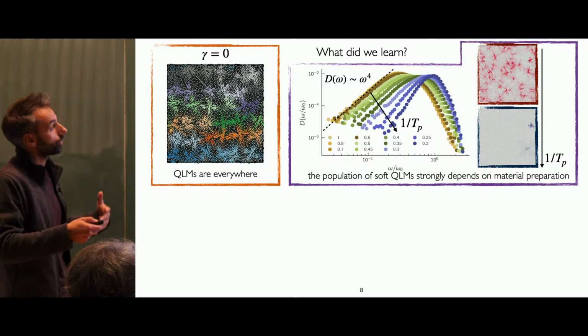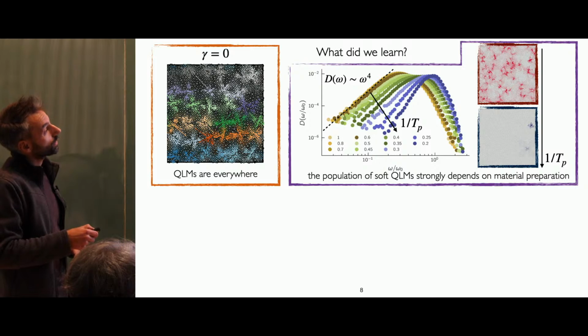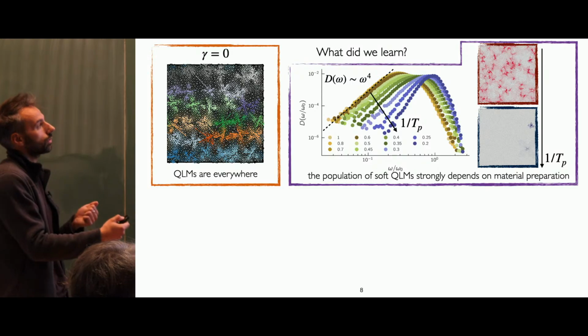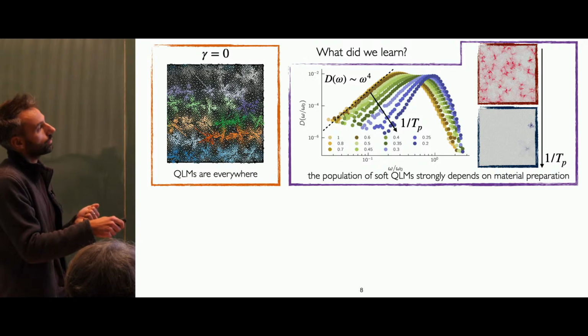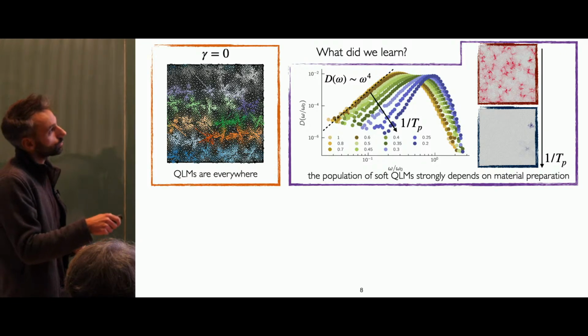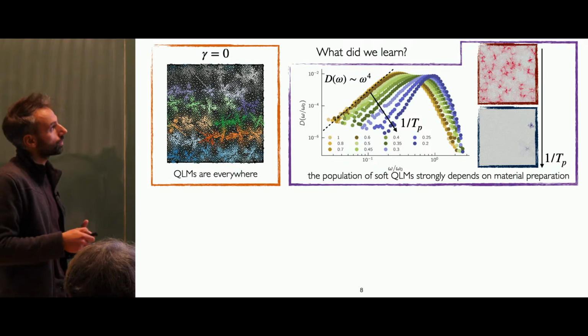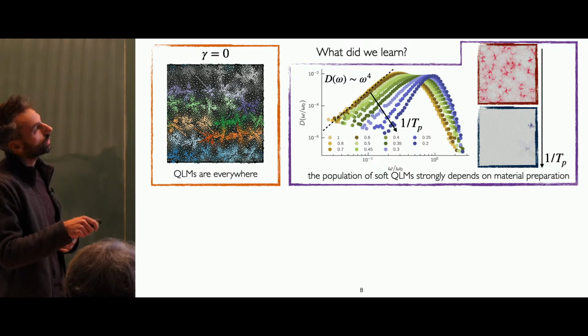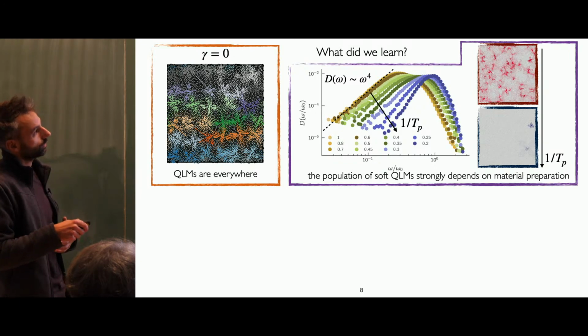And one thing that this community, not only me, but many people in this room, learned is that in the low spectrum we found a peculiar statistic for these modes. It follows omega to the 4. And what was interesting is that depending on how you make your glass, if you quench it very fast or very slowly, so this will be my temperature, high temperature and low temperature in blue, you see that you really have a depletion of soft spots in your system. So the picture is that poorly annealed glasses have a lot of weak soft modes, and very stable, well annealed glasses will start to have a depletion of these modes and a depletion of the prefactor of this density of states.